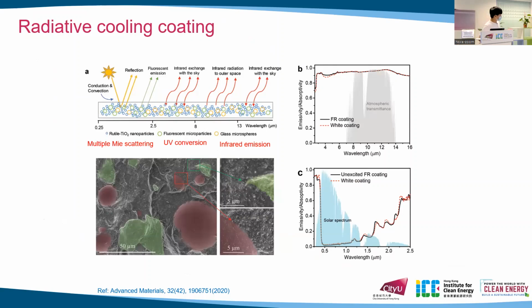It consists of a polymer matrix and 3 functional pillars. First, the polymer matrix used in this coating is a waterborne emulsion, so it's eco-friendly. And the first pillar, titanium dioxide nanoparticle, is a commonly used coating material. With proper size, it can provide sufficient multiple Mie scattering and make the coating a white appearance. But as we all know, TiO2 has intrinsic UV absorption. So the solar reflectance of TiO2-based white coating can only reach 88 or 89%.